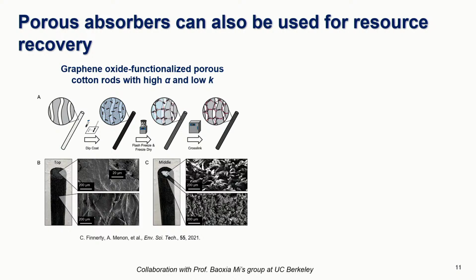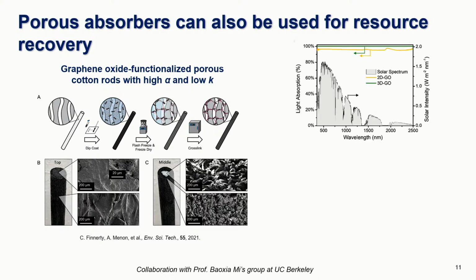And here now, again, the material becomes important because we have to be able to absorb the solar radiation. And so we use graphene oxide, which we can functionalize. We just take a cotton rod and functionalize it with graphene oxide. And we can get the desired properties. So this is just some SEM images. And you can see the outer surface of the cotton rod is all covered in the graphene oxide. But if we cut it at the middle, you can see the inside is still very much just the cotton. And so that's where the capillary wicking is happening. And then that water is evaporated from the outer surfaces, which are coated black with graphene oxide. So it has a very high solar absorption. So that's what I'm showing you here.